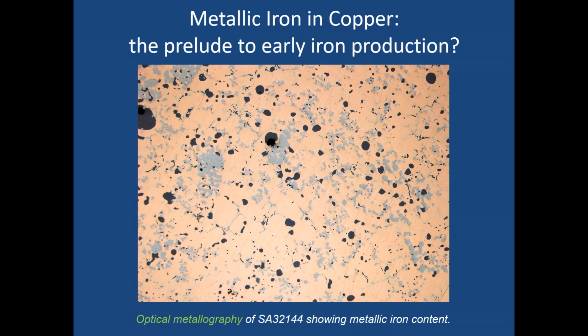at the site. And this gets raised when we consider copper, because it's clear that when they were producing copper, they were also inadvertently smelting iron at this site. This is a section of an ingot of copper, but all of these silver areas that you can see with these unusual shapes, they're actually metallic iron that was being smelted at the same time and that was mixed in with the copper. And I did wonder when we began work at the site whether all of the iron work that we saw somehow related to the iron that was being produced during copper smelting.